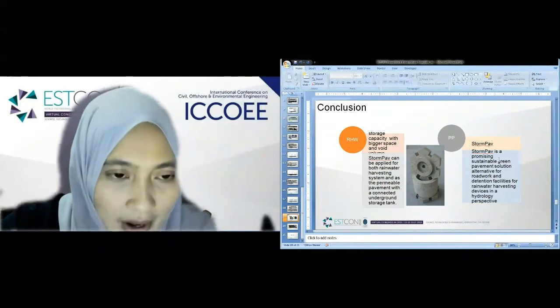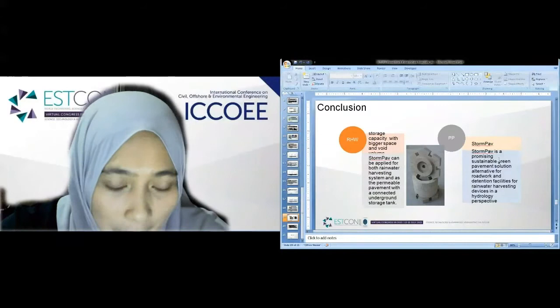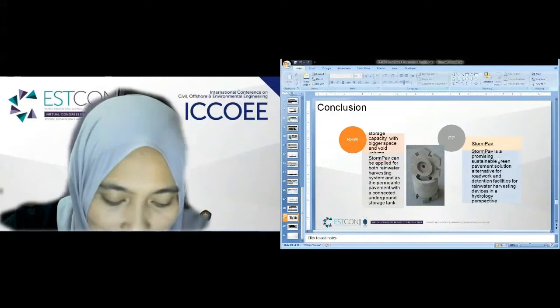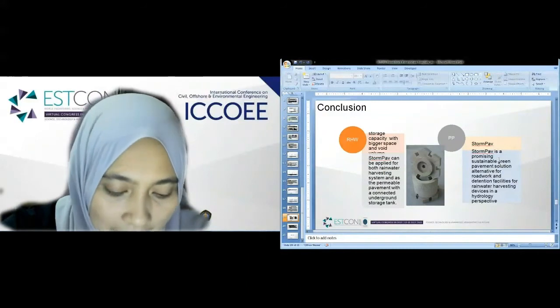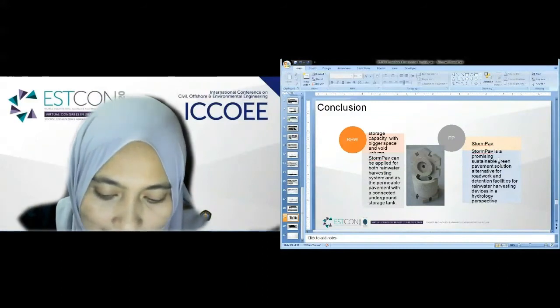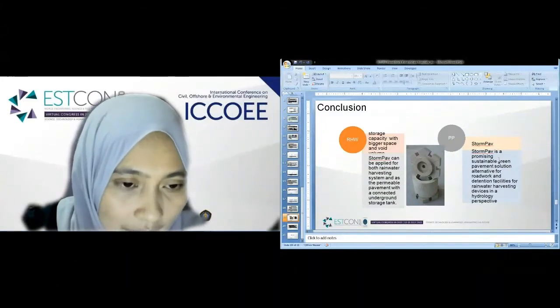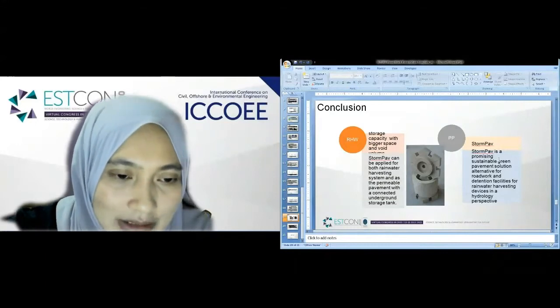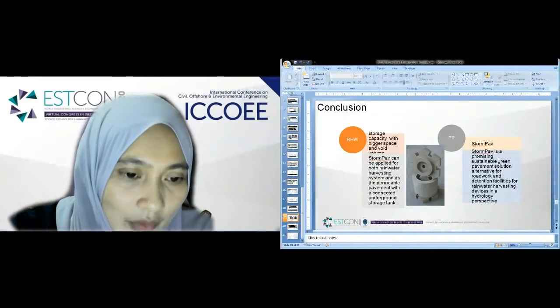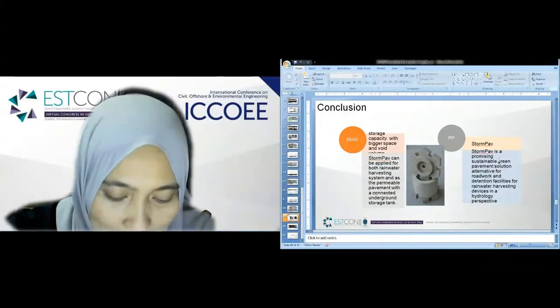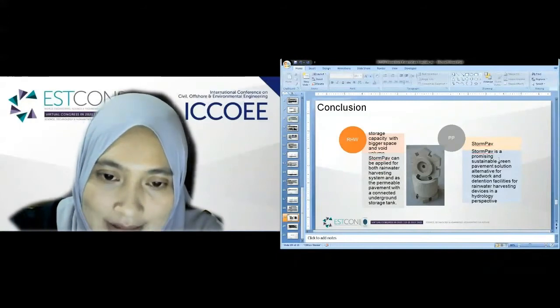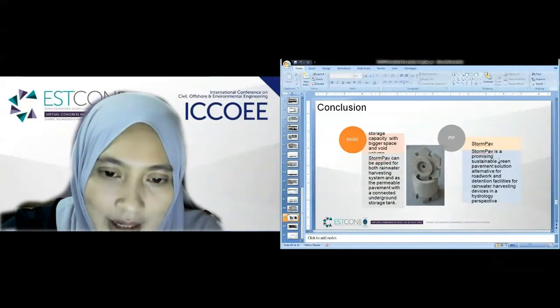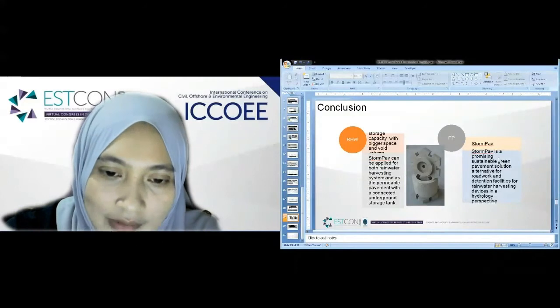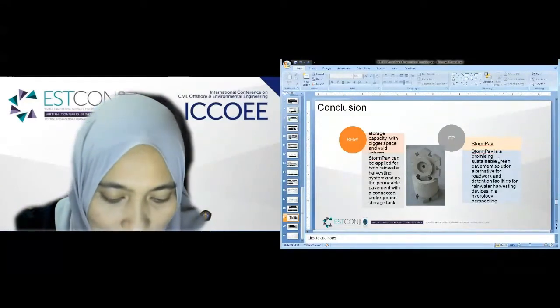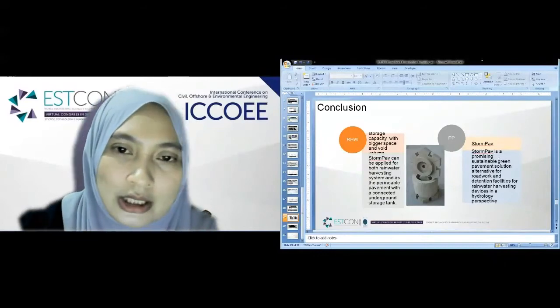In conclusion, the StormPav has shown unique hydrological features which prove advantageous, with a bigger space and void capacity of about 60 to 70% compared to other permeable pavements. The experimental results concluded that the StormPav can be applied both as a rainwater harvesting system, as micro detention storage, and as a permeable pavement with a connected underground storage tank. Therefore, the StormPav is a promising sustainable green pavement solution and alternative for roadwork and detention facilities for rainwater harvesting devices from a hydrological perspective. With that, thank you so much.